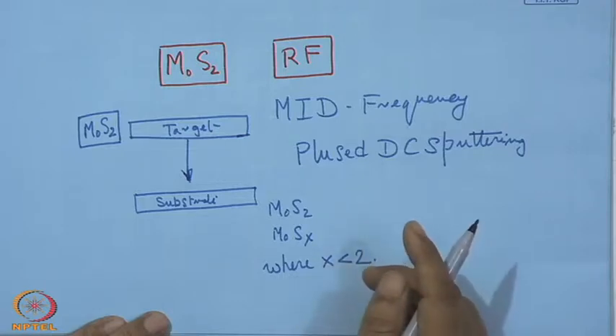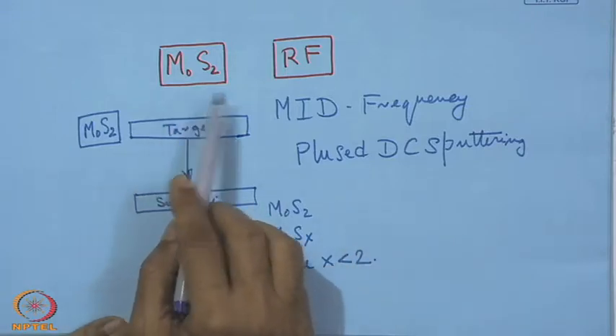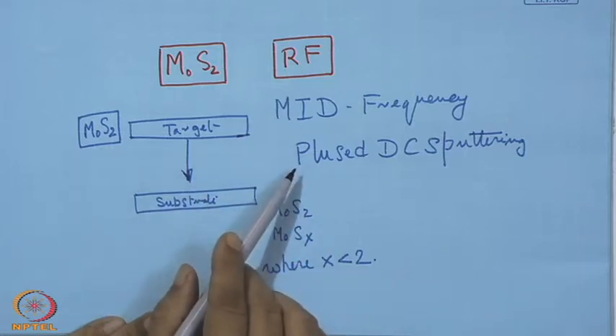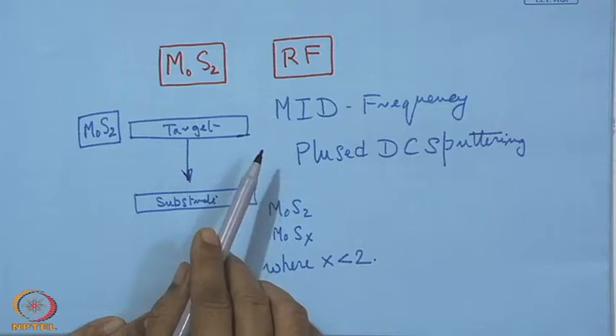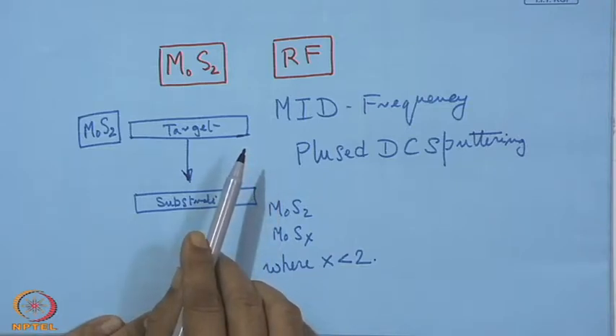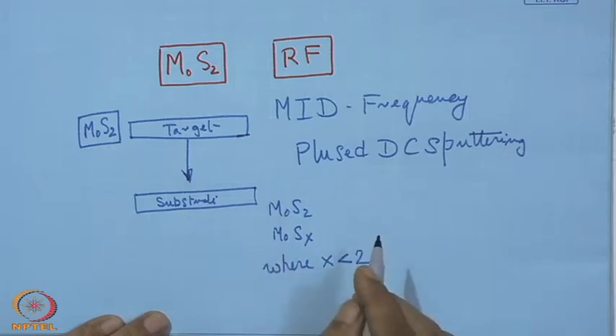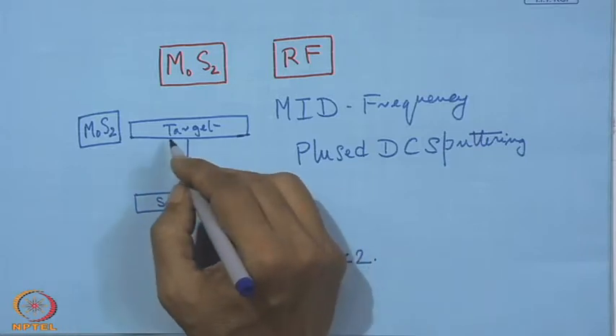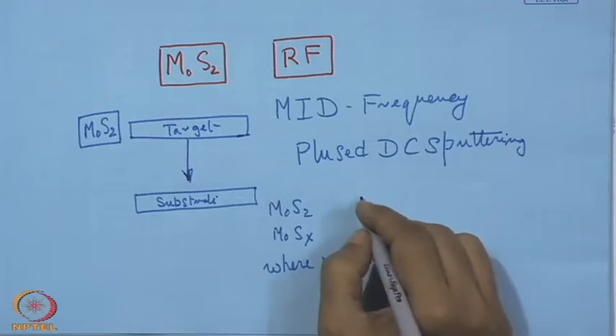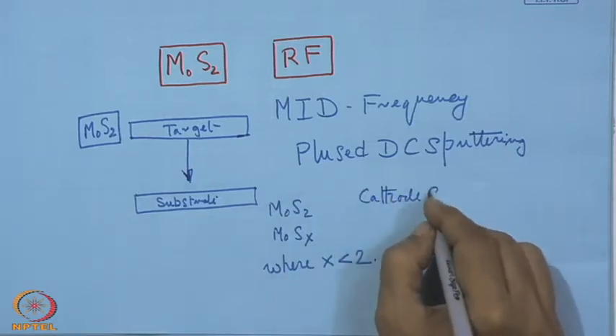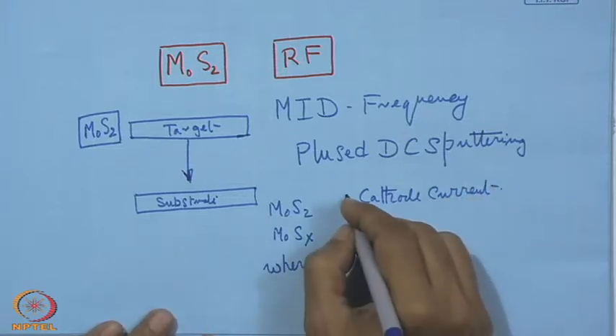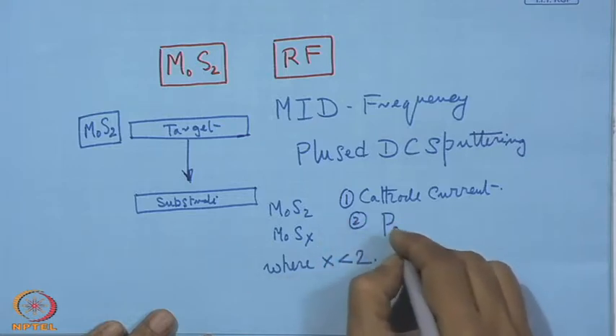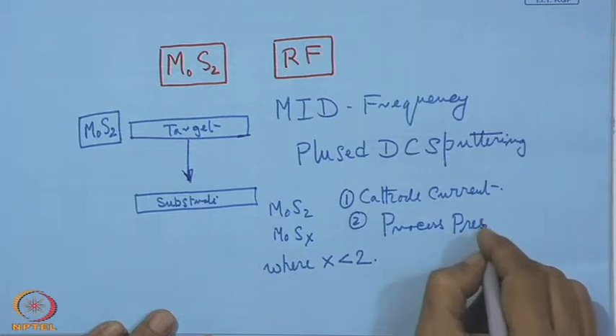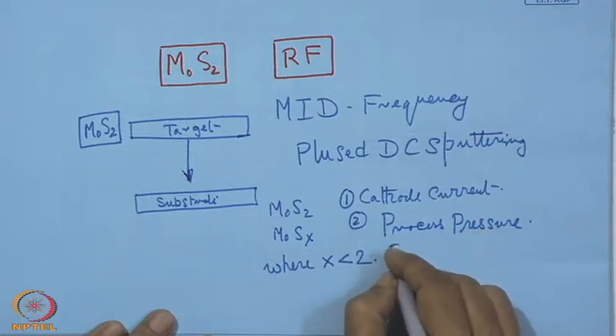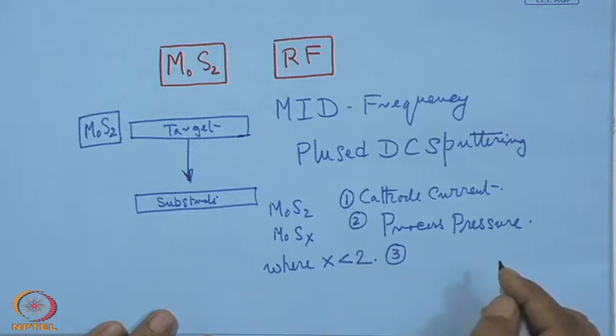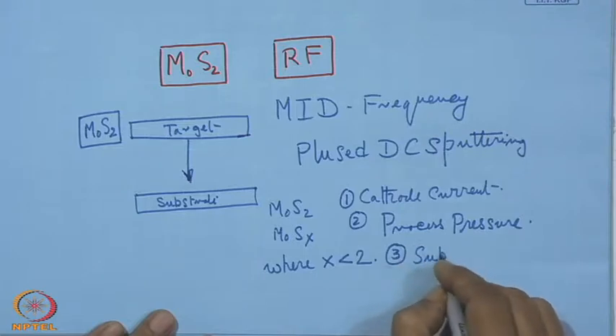And at the same time, there is another way of doing it. This is applicable whether it is RF or mid frequency pulse DC sputtering, and in this case definitely the parameters which are going to influence this value of x are, on one hand, the cathode current, that is the set value of cathode current. This is number 1. Number 2 is the process pressure, that is also another parameter. And number 3, what also appears to be quite important and can influence, is the substrate bias voltage,